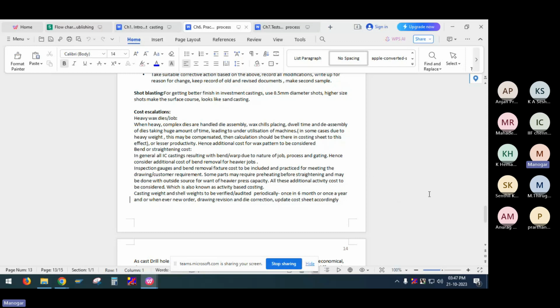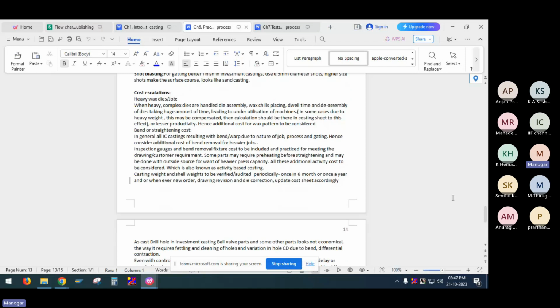And we always have a bend or warp in the investment casting. Then we have to consider the cost for bend removal and any gauging required to meet the dimension tolerance, then gauging time, that grinding of the casting as per gauge or bend removal using the gauges, all that will add a cost and time. So these things we have to consider. And some components cannot be straightened at room temperature, then we have to preheat and do bend removal. That is also there in some of the cases that I come across. So all these you have to consider during quotation or costing time, or you should add a point in your costing sheet.